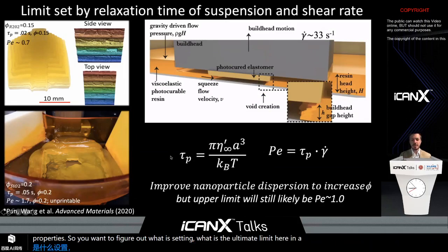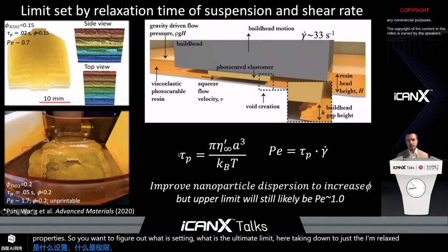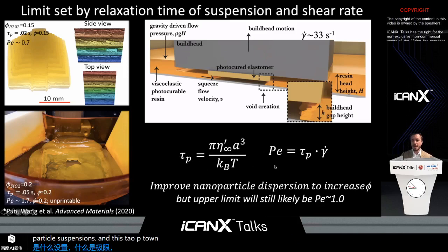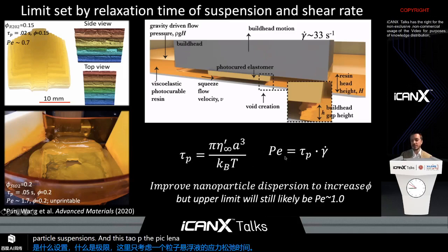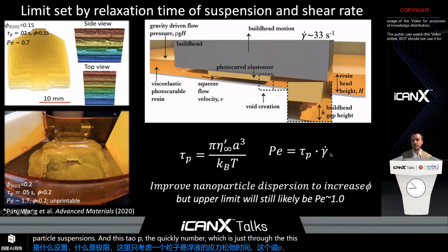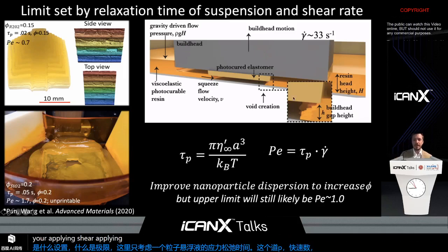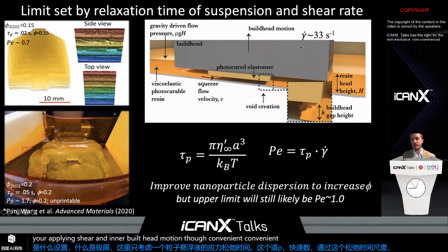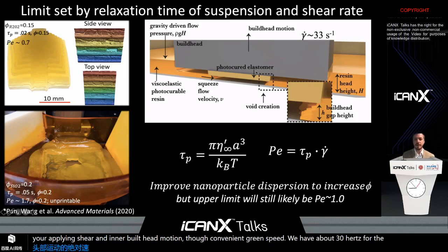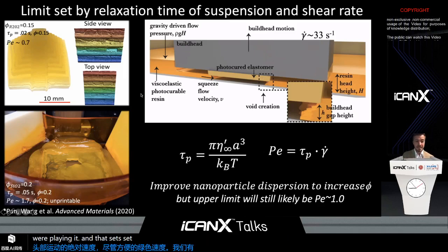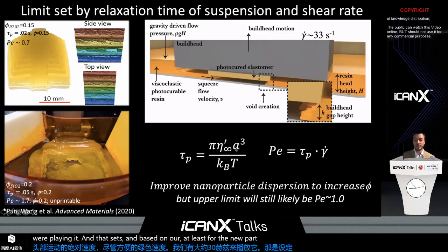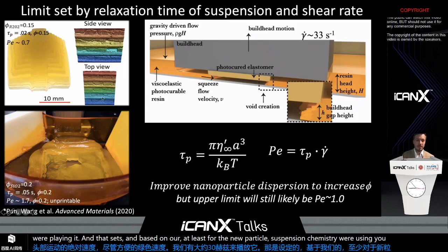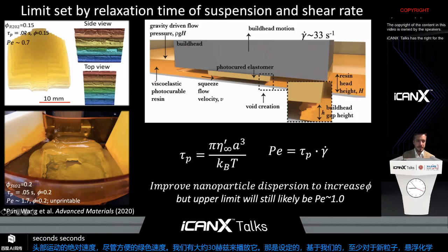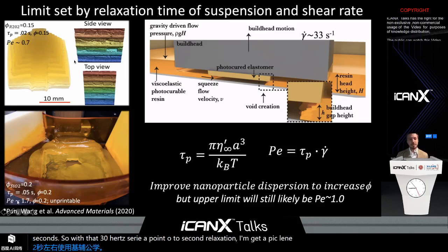And it came down to just the stress relaxation time of nanoparticle suspensions, tau p, and then the Peclet number, which is just this relaxation time scale multiplied by the rate at which you're applying shear. And in our build head motion, at a convenient print speed, we have about 30 hertz for the shear rate that we're applying, and based on, at least for the nanoparticle suspension chemistry we're using, a tau p of around 0.02 seconds. So with that 30 hertz shear rate and the 0.02 second relaxation time, you get a Peclet number of about 0.7, and this is printable.